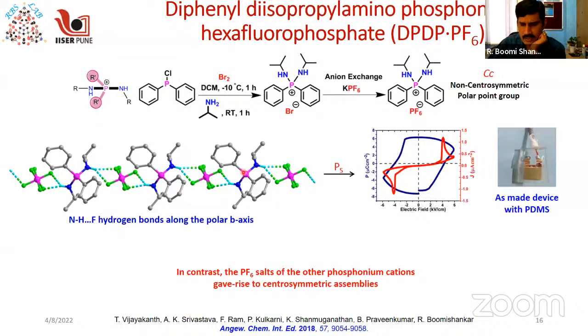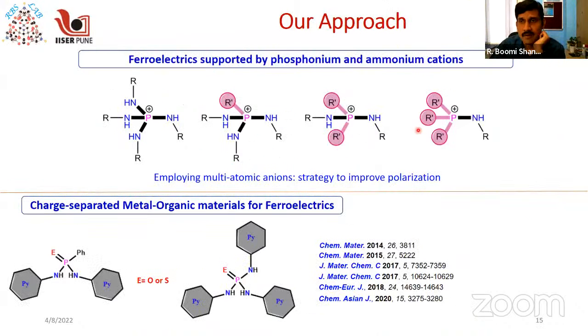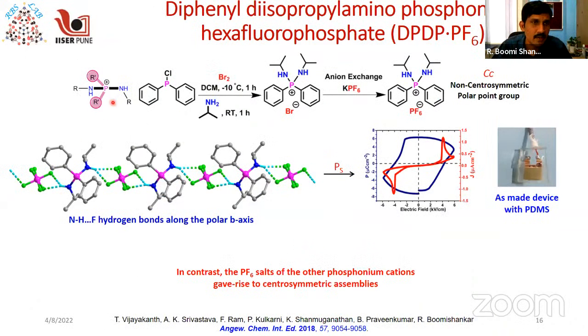In our approach, as I told you, we have played around with the aminophosphonium scaffolds. The first success came when we prepared this diisopropylamino phosphonium salt with two phenyl groups, called the diphenyl diisopropylaminophosphonium compound. This can be prepared by a small synthetic procedure like this. You start with the phosphine with two phenyl groups and one chlorine atom, oxidize this with bromine, substitute with the primary amine group, and eventually do an anion exchange, because the monoatomic anions were found to exhibit very low polarization attributes.